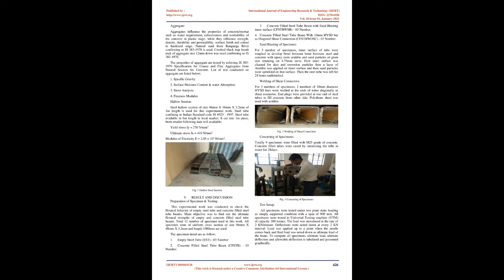He concluded that a substantial increase in the moment of resistance and the corresponding curvature of all the hollow sections used in the experimental investigation is observed due to concrete filling, and the CFT specimens exhibited a higher ductility than the hollow sections. An increase in the wall thickness of the steel tube increases the moment of resistance and ductility of both the hollow and CFT samples. An increase in strength of infilled concrete for a given wall thickness of a CFT specimen does not help in increasing the moment carrying capacity to a great extent.